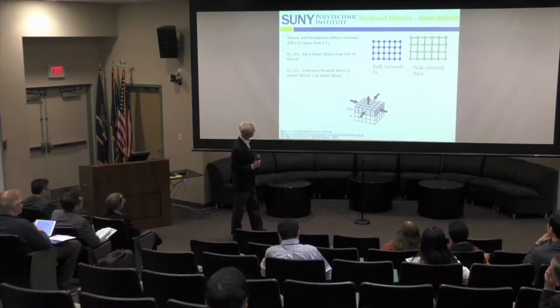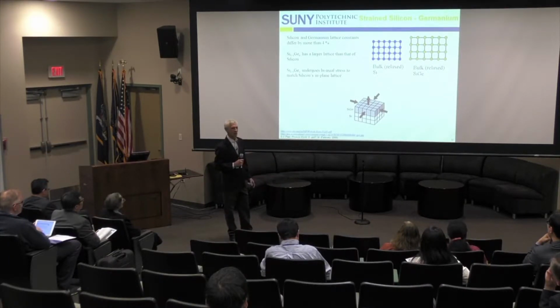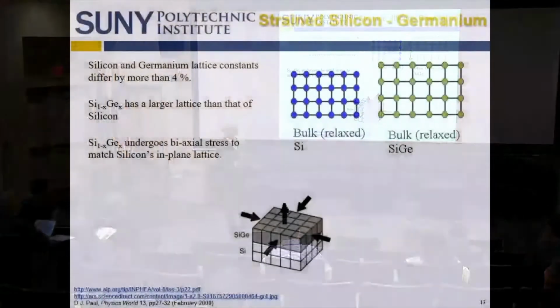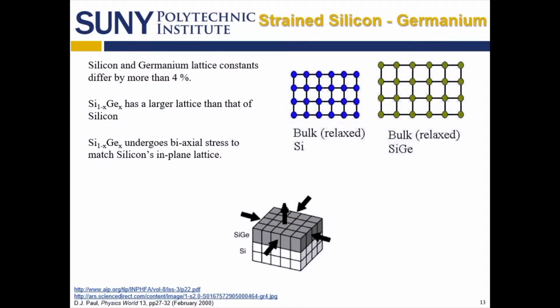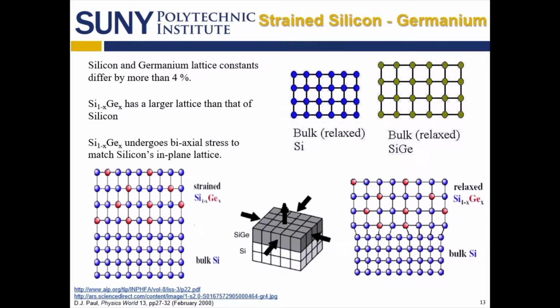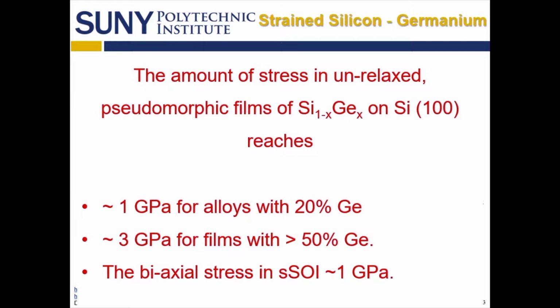All right, there's another aspect to all of this. If we're making silicon germanium structures, silicon germanium has a lot of biaxial stress in it, and that biaxial stress can be relaxed when you have a fin structure. So how much stress is in this silicon germanium structure? Here we see that if you pseudomorphically grow, or have a good epitaxial structure, there's going to be a lot of stress in that silicon germanium layer. It's going to be compressed biaxially, and if it relaxes, that's important. You have a phenomenal amount, 3 gigapascals, if you have 50% germanium in your silicon germanium, and that's more than the famed strained silicon on insulator wafers that used to be a hot topic in the industry.